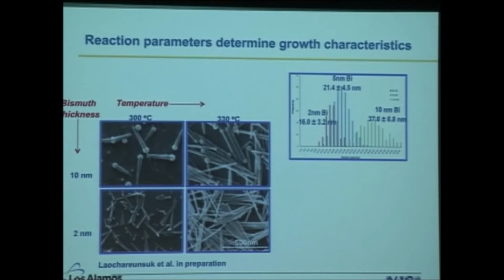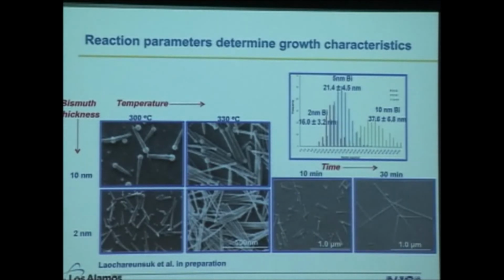Temperature, small increases in temperature dramatically increase the length of the wires we achieved, and also you can see here the diameter was greatly influenced by the thickness of that bismuth, going from 2 to 5 to 10 nanometer thick films. Our wires changed from diameter 16 to close to 40. Time was a big player. You go from 10 minutes to 30 minutes of reaction time, and the wires are over a micron.